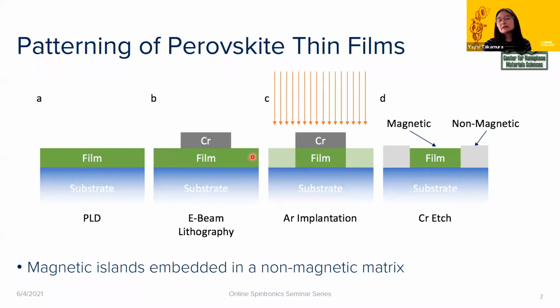Depending on how thick the film is, we tune the argon ion implantation energy. For a thicker film, we'll use a higher energy; for a really thin film, we'll use a lower energy, just to get the projected range of the implant to be in the center of the film. So that's actually in the fabrication part, right? The measurement itself should not do anything. Yes, the measurement itself should not do anything. It's just X-rays, a non-destructive process: X-rays in, electrons out. Okay, great. Thank you.